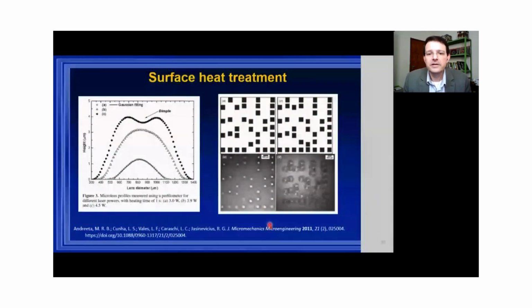Here you can see two different approaches to heat treatment on glass. You have microlenses created through very fast heating. You expand the volume of the glass locally and create a Gaussian shaped lens. But if you increase the size of those lenses, you create a dimple because it cannot sustain itself anymore, so it makes a little dimple on the top.